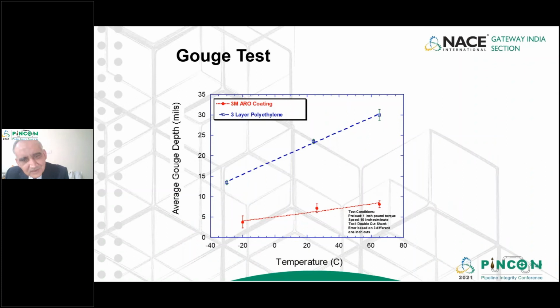There are so many tests, but one of the most important tests is the gouge test as per CSA. Now, what is a gouge test? A piece of coated pipe is taken into the lab. About 50 kilogram weight is applied through a very hard burr, and the panel is pulled in a horizontal direction. So the hardened burr will actually inscribe into the coating. So what we did is we compared 2 panels. One is a 3-layer polyethylene coated panel and an ARO layer coated panel. So we see that the blue line is representative of the 3-layer polyethylene coated pipe piece, and the red line is representative of the ARO coated pipe piece.